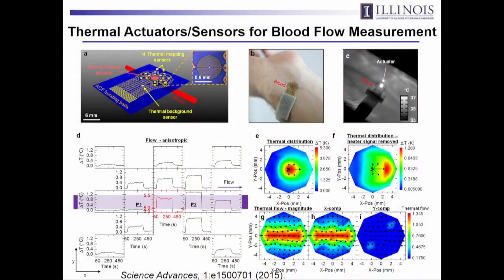So if you take one of these devices and you reconfigure it so you have a radial array of precision temperature sensors with a thermal actuator in the middle, and you align this thing with an underlying blood vessel, such as an artery, then the resulting distribution of temperature induced by activation of that thermal actuator is anisotropic, because it has a directionality associated with the direction and the volumetric rate of blood flow. And so you can see that in this temperature map, it's skewed in the direction of blood flow, and with quantitative models of the 3D thermal diffusion physics, you can extract from that degree of anisotropy the volumetric flow rate of blood through that vessel.